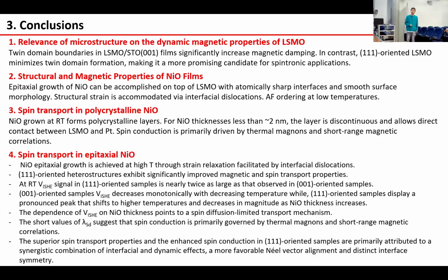And the 111 oriented heterostructure exhibits significantly improved magnetic and spin transport properties. At room temperature, the inverse spin Hall effect voltage in the 111 oriented sample is nearly twice as large as that observed in the 001 oriented samples. In the 001 oriented sample, the inverse spin Hall effect voltage decreases monotonically with decreasing temperature, while the 111 oriented sample displays pronounced peaks that shift to higher temperature and decrease in magnitude as the NiO thickness increases.